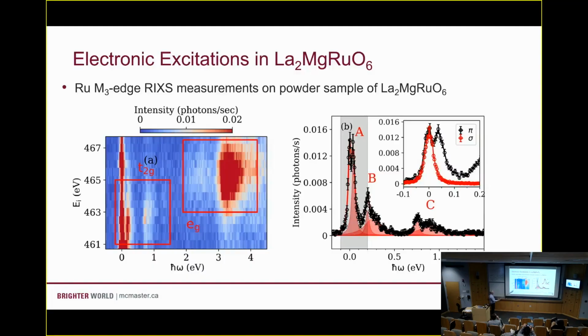What you've got on the left here, this is a map showing a RIXS spectra here. So this is photon energy transfer as a function of incident energy. And what you can see is we are varying the incident energy here. We're going through these ruthenium resonances. And so what you see is that these inelastic features that become very sharp, very intense, this is occurring when you're getting these resonant effects. Okay? And so we've got basically a set of features that resonate here, okay, at a slightly lower incident energy than the features here. This doesn't just give us element sensitivity, it also gives us orbital sensitivity. Okay? So this gap lets us associate these features with transitions within the T2G states, and these features with T2G to EG transitions.